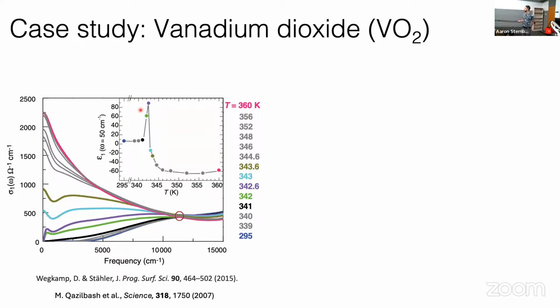So the resistivity is perhaps a natural way to look into the electronic properties of this system. The optical conductivity at low frequencies gives you a measurement that should agree with your DC resistivity. At higher frequencies, the optical conductivity is impacted by scattering and interband transitions, and so you see some structure. What you can clearly see is that this blue curve, which is the insulating phase with low conductivity, and this pink curve with metallic-like conductivity are attained below and above the insulator metal transition temperature, respectively. However, when you're in the vicinity of the transition at intermediate temperatures around 340 Kelvin, you see values of the optical conductivity which are intermediate, which is surprising, again, because this should be a first order phase transition.